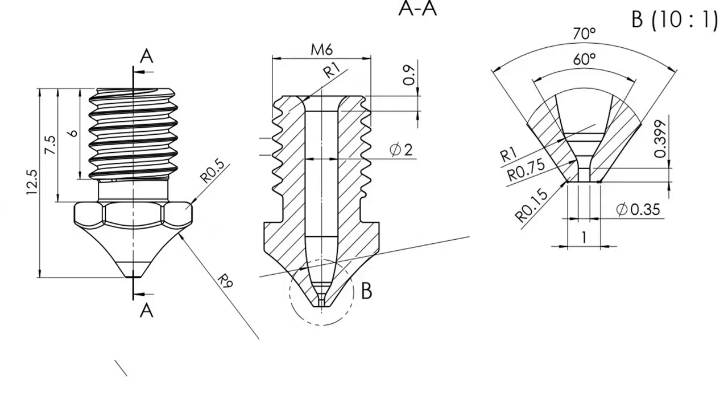For this, we have some basic design rules that illustrate the optimal geometry. The first is avoid sharp inner corners because they could set off cracks during sintering. Secondly, avoid high wall thickness, which make the debinding of the part more difficult and could lead to voids in these areas due to the big temperature differences while cooling down after molding. And as last, try to have equal wall thickness. Otherwise, this could increase the chance of distortion of the part due to tension differences during sintering, or better said, during the shrinkage.